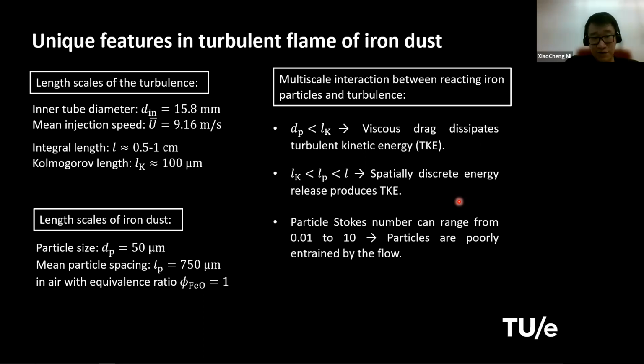And the last remark, I think, is even more interesting and more unique to iron combustion, is that the particle Stokes number can range, depending on whether you're talking about the Kolmogorov length scale or integral length scale, from 0.01 up to 10, right? So Stokes number is the measure of how well the particle can be entrained by the flow. Right, the smaller the Stokes number is, that means the smaller inertia the particle has, then the particle can be more easily entrained by the flow.